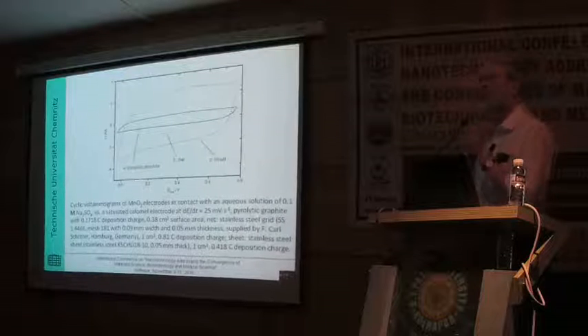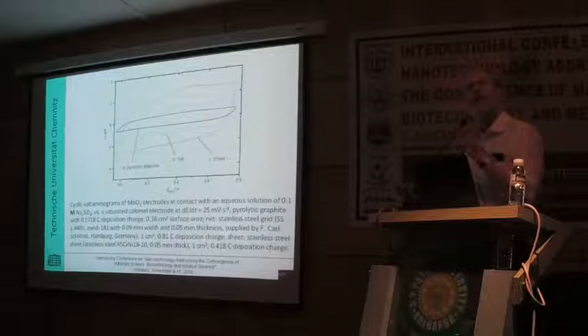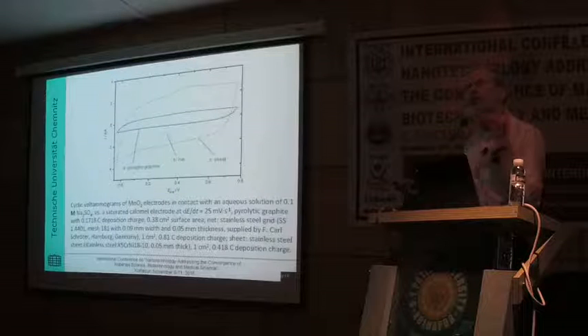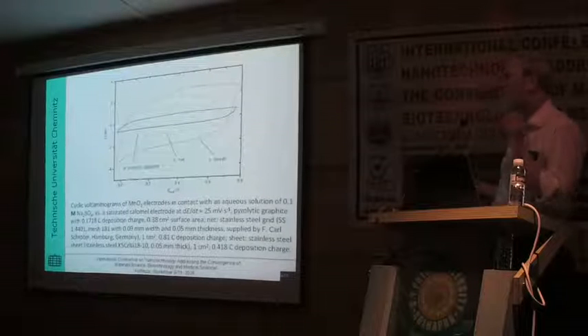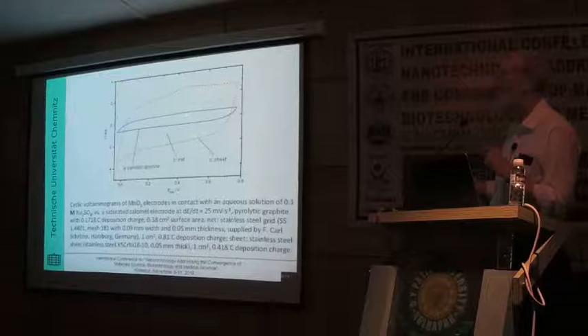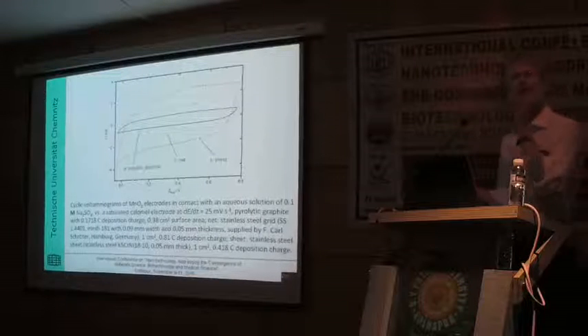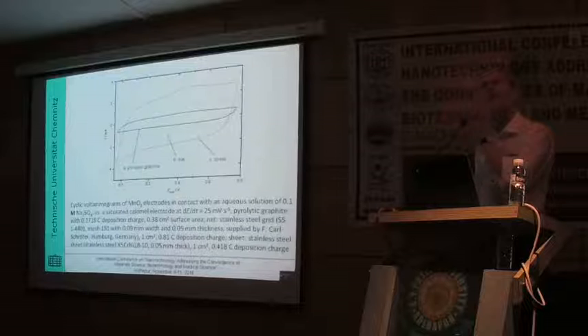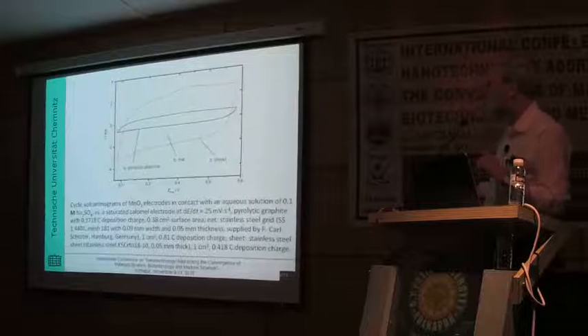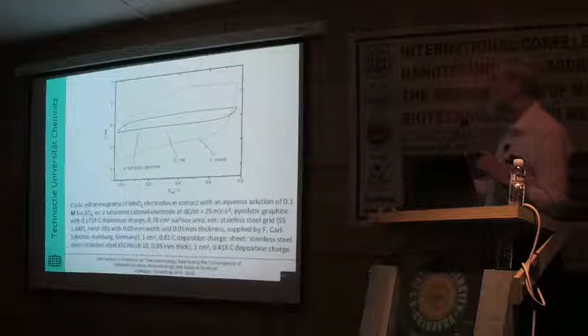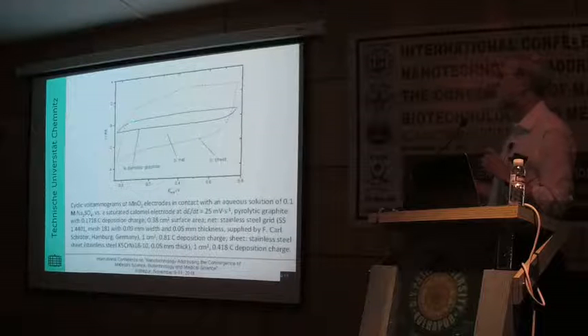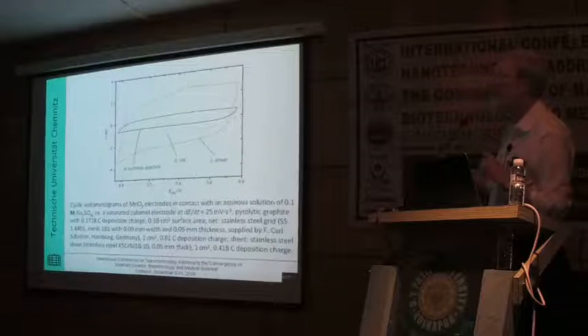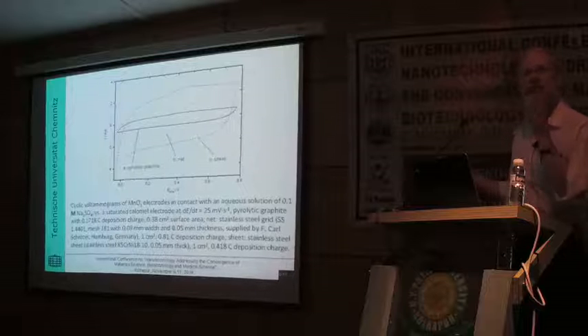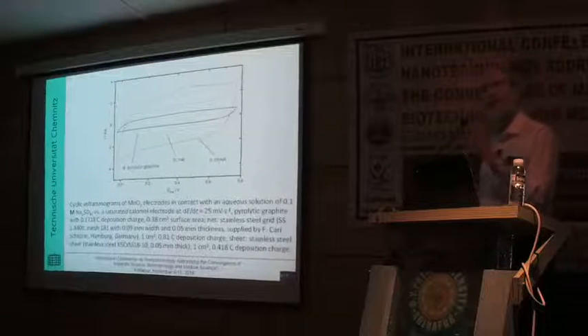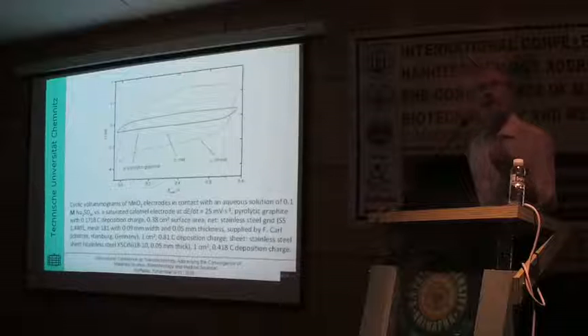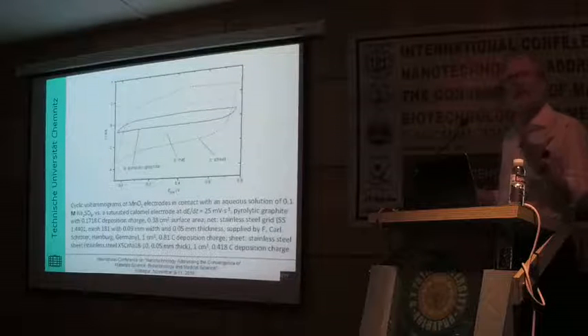The response of this material is like the response of a capacitor. Although we all know in this room, this current response is due to the change of the manganese 4 to the manganese 3 ion when we go this direction, or when we go this direction, the manganese 3 into the manganese 4. And only at this point you see a small, oblique wave, and such a current wave, or more precisely a current peak, we would expect from a redox process.